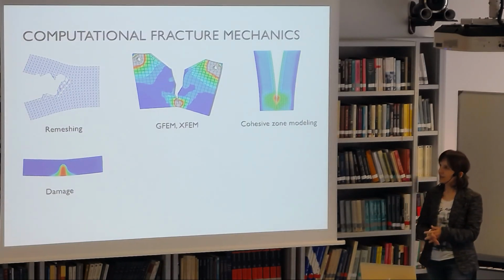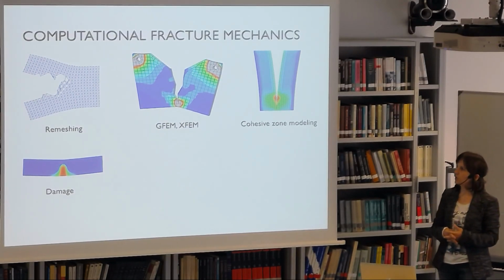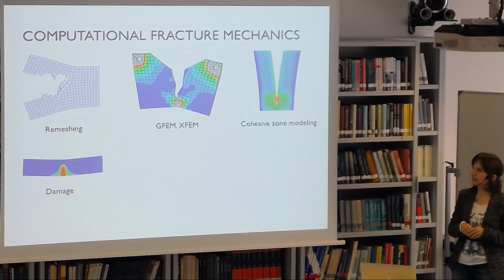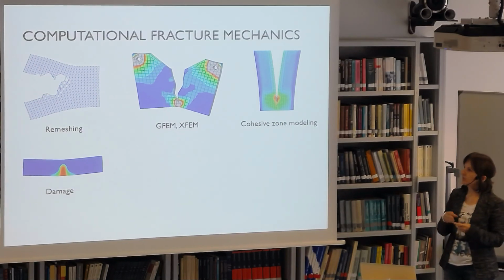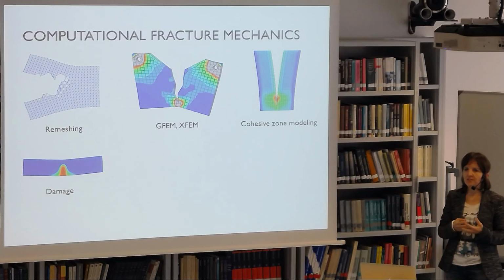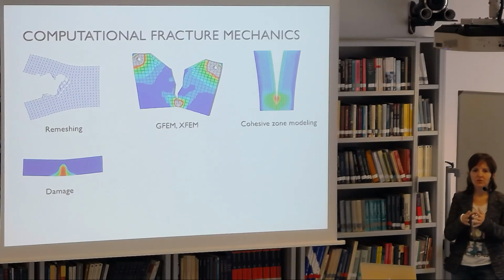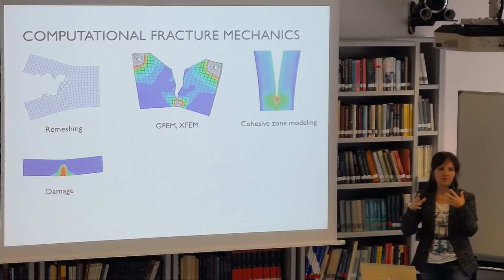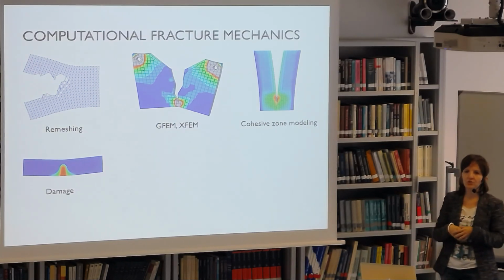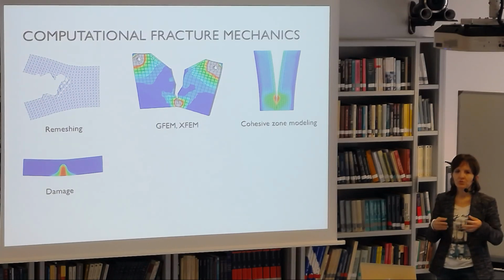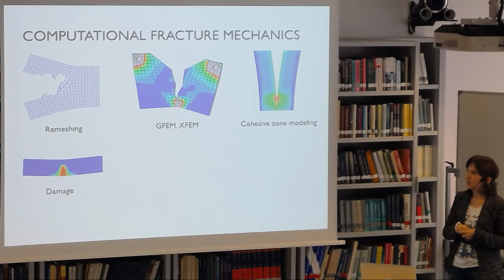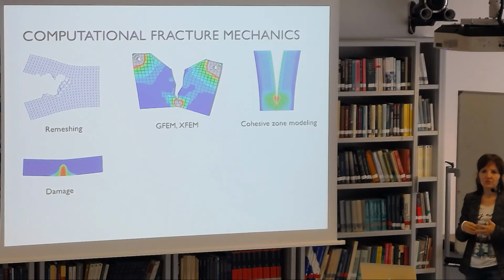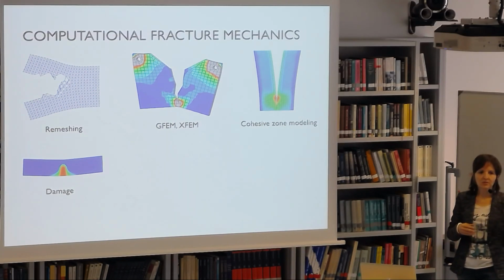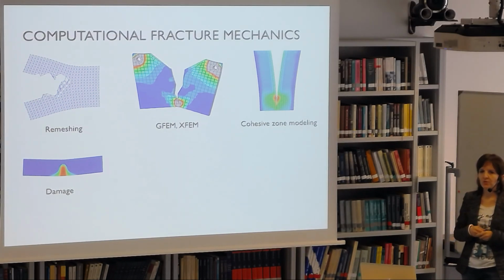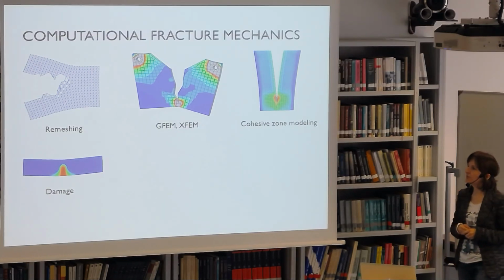So, computational fracture mechanics has a lot of possibilities. I'm not listing all of them by any means. I'm just listing some popular approaches. Remeshing is a possibility in the finite element setting. You have some thresholds. As soon as the threshold is met, you disconnect nodes and so have criteria for crack advancement. You need, of course, a lot of criteria. You need criteria anytime two cracks want to merge in one, or one crack wants to split. You need criteria for the direction of the crack and so forth. And also you need projections between different meshes if you have history variables, for instance in plasticity, or if you have other types of complex material models.